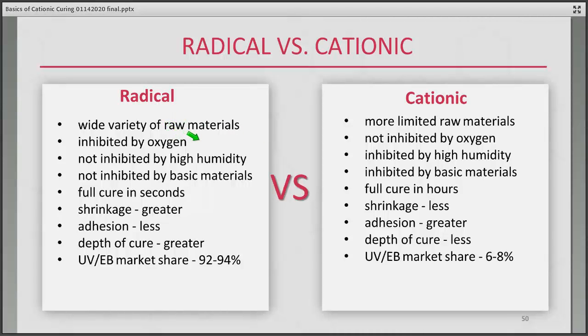Radical chemistry, UV curing, is inhibited by oxygen. In some applications it doesn't matter. However, in others, it's a real challenge to work around or an expensive problem to have. You may have to have a nitrogen blanket. You also have in radical chemistry, it's not inhibited by high humidity. Cationic, because of the mechanism, there is no oxygen inhibition, so you can just run right in the open air and it will cure very well. However, you then get potentially inhibited by high humidity at times. It may not fully kill it off, as we've talked about adding water, but it will still vary your rate of reaction, so you'll see a change in cure speed.